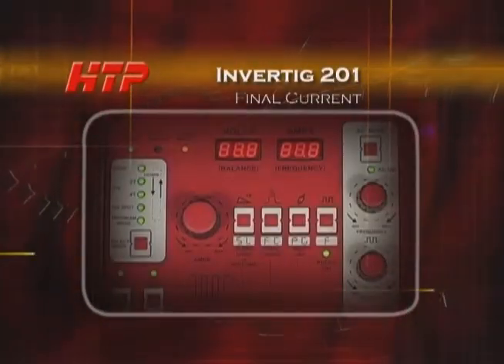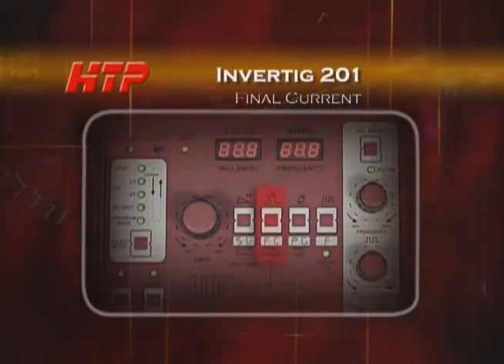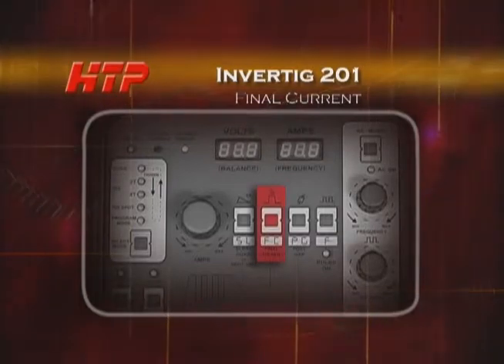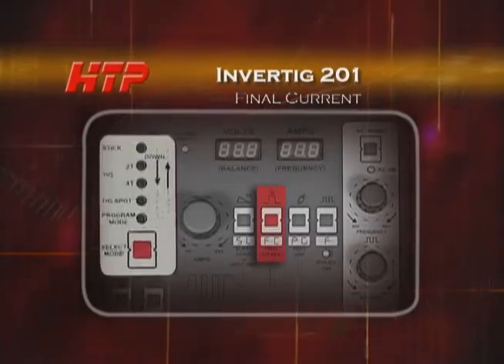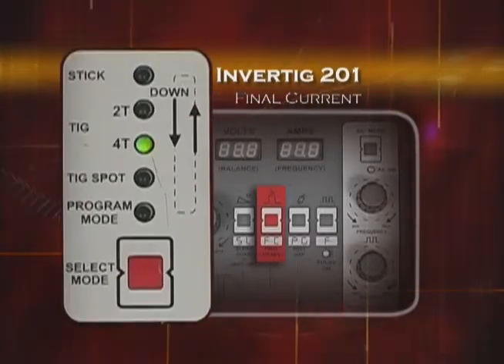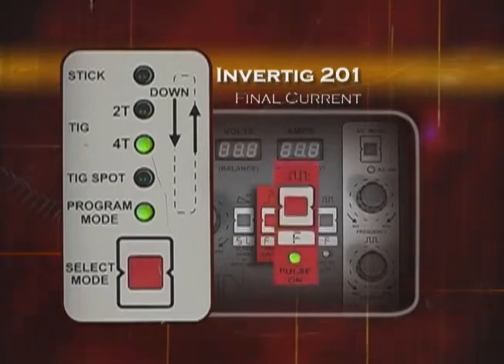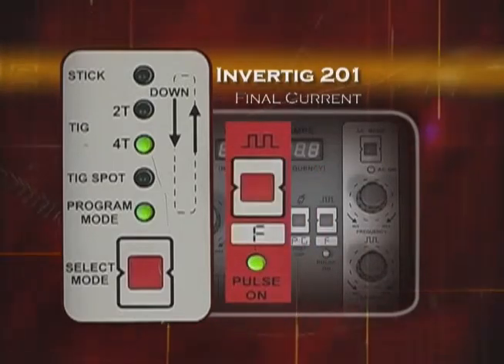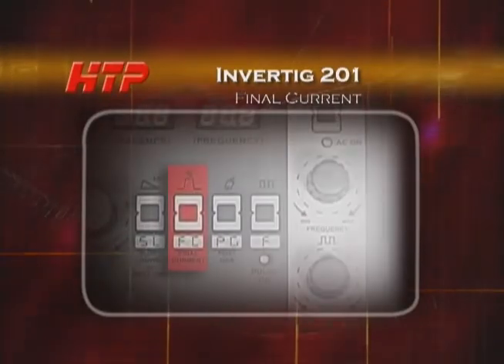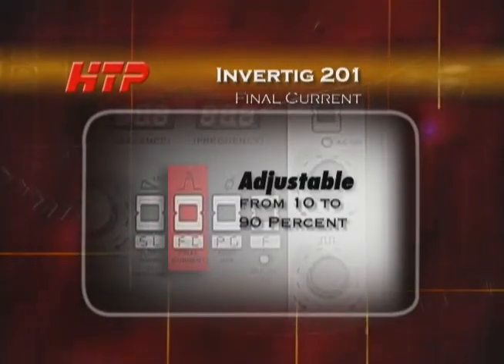Final current is the welding amperage the machine slopes down to. Depressing this button allows you to adjust the final current. This is only applicable when your InverTIG 201 is set in the TIG 4T mode, the program mode, or the pulse mode. The final current is adjustable from 10 to 90% of the base current that is set by the amperage adjustment